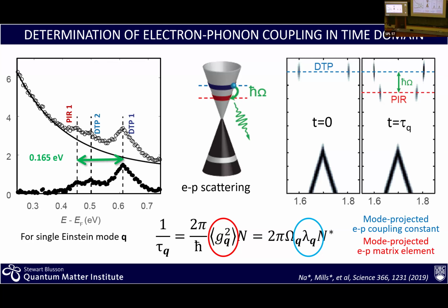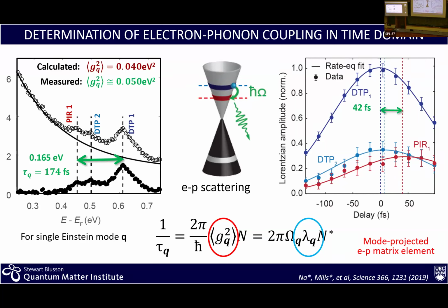So here is a spectrum up here. You can see a tail of electrons relaxing down to the chemical potential. You see some structure in here. If I subtract the tail, these in blue are two optically allowed transitions in graphite, not graphene, but it's very similar. And then there is a peak that you see at an energy which corresponds exactly to the energy of a phonon. And if you follow this in time, so this is the delay between pump and probe, you're going to see that for the blue transition, the optical transition, the maximum is taking place where pump and probe are coincident. You're directly promoting electrons into the unoccupied side. However, if you wait long enough, there is another peak coming up, and this is a maximum at about 50 femtoseconds or so later. This particular peak is the electron that falls down by emitting a phonon.